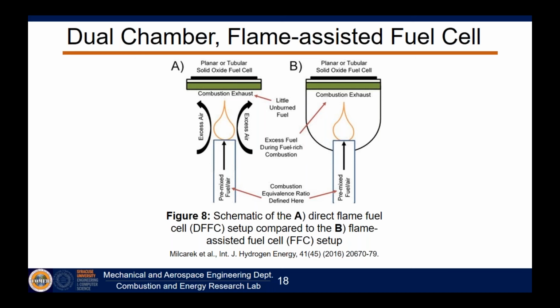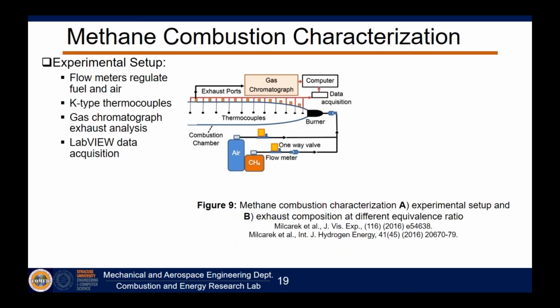And so the first thing we needed to do, and this is what we did with that Amtech project, is we developed a combustion chamber. We took our fuel. In this case, we were studying methane because methane is a pretty good model for natural gas. Most of natural gas is methane. We mixed it with air, and then we supplied it here with a burner. This burner is basically the same dimensions as a typical in-shop burner that you have to heat your house. And then we have the combustion process happening here. We're monitoring the temperature, and then ultimately we're going to pull exhaust from it.